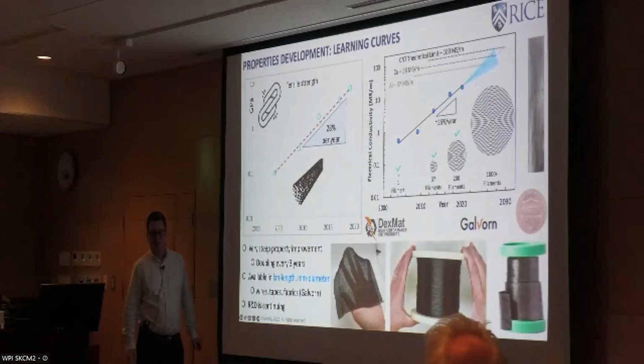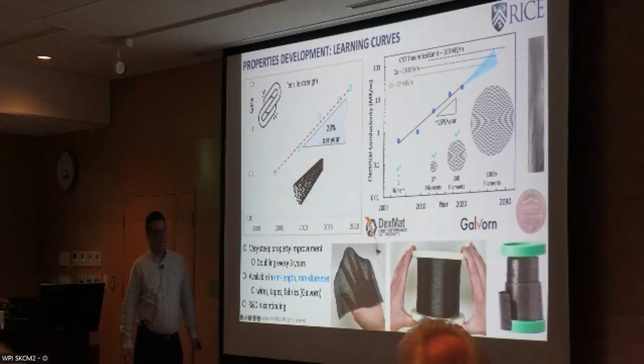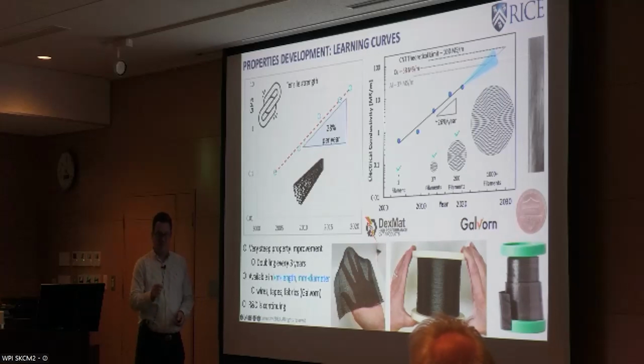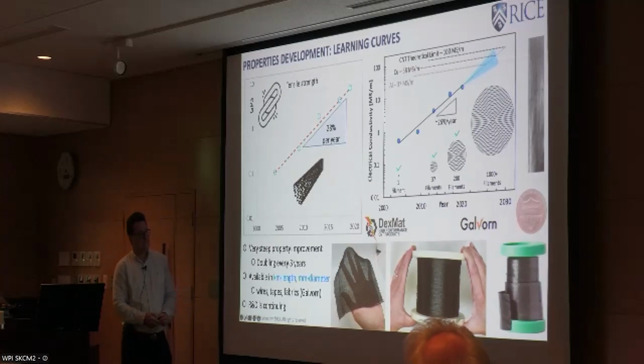Yeah, of course. Can you do something similar with graphene? It doesn't hold as well. It's the reason why, if you think about the surface area per unit volume and the length. So these nanotubes that you have in your hands, the individual nanotubes are about 10 microns long, about 2 nanometers in diameter. So the surface area of the individual is massive. And they pack really well because of cylinders. Graphene, yes, you can, but typically what we see when we've done it is it's more fragile.